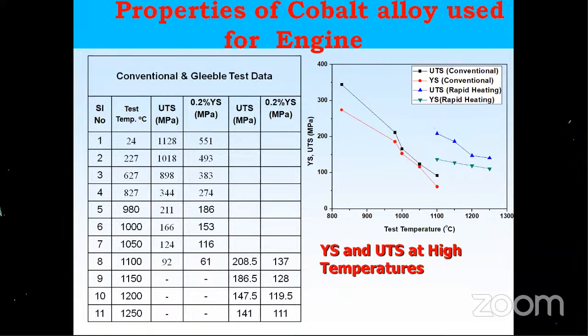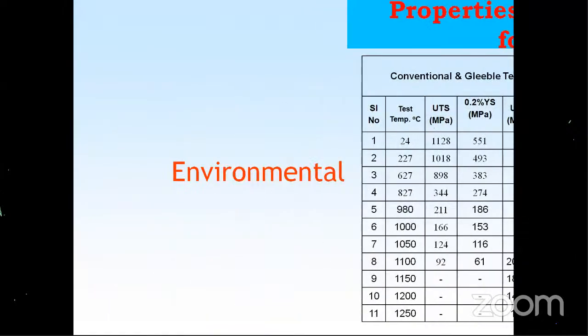So what I mean to say is, since we have a small flight period, 150 seconds, the material is retaining most of its strength. But if you increase the time from 150 to 500 or 600 seconds, the strength value changes. But for the present launch vehicle missions we are using, this is the margin we are getting. We have sufficient margins, there is no issue. So what I mean to say is, if the composition is ensured, the material gives such strength. Then we have environmental issues.